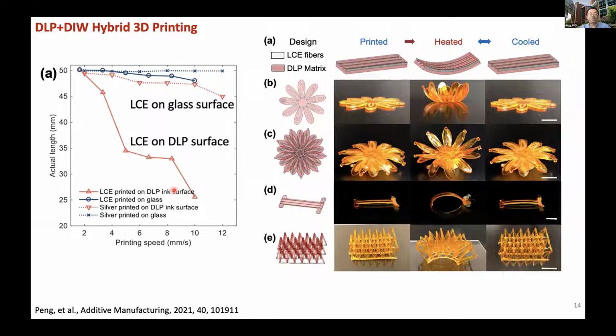So after printing, the top surface is kind of wet and also a little bit tacky. This makes the LCE not stay on the surface very well. You can see here, if I make my printing speed very low, yes, I can make the length I get roughly the same as what I want. But if I increase the speed, the LC ink contracts significantly. Here I'm trying to print about a 50 millimeter long LCE line, but if I use a 10 millimeter per second moving speed, the LCE is only 25 millimeters in length, so you actually lose half of the length.